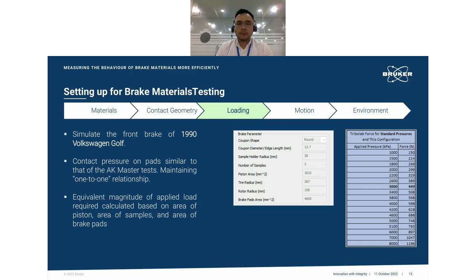While applying contact pressure on the brake pads, similar to that of the AK Master test, where we have various contact pressures ranging from as low as 1 megapascal all the way up to 8 megapascal. This is to maintain a one-to-one relationship so that the coefficient of friction or the test results will be more comparable and we can see similar trends. So the equivalent magnitude of applied load required is calculated based on the piston area, area of samples, and area of the brake pads. We have the software that helps us do all the calculations and give a set of test parameters that we can just directly use for the simulation.